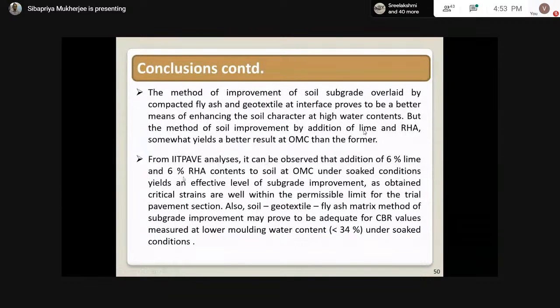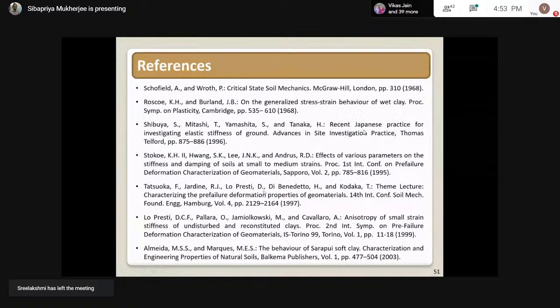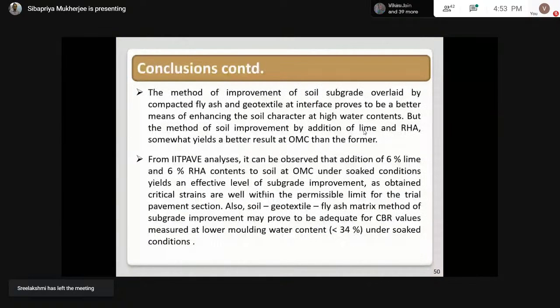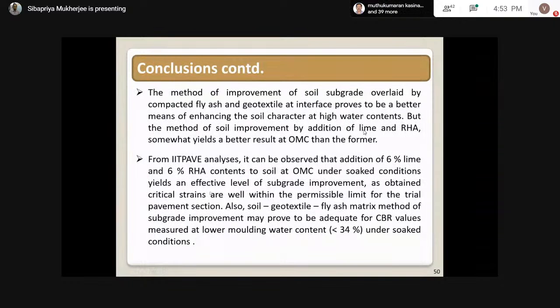So the IITPAVE analysis also supplements the same thing, as we see that this 6% lime and 6% RHA content mixed with the soil at OMC under soak condition yields an effective level of subgrade improvement as obtained. Critical strains are well within the permissible limit of the trial pavement section.